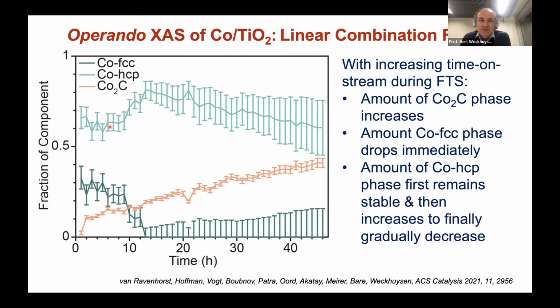And now you have just to believe me that this is then the one which, in our opinion, fitted the best. And what you notice is that cobalt carbide increases as function of time. And then something peculiar happens. Seemingly, the FCC is first consumed at the expense of the carbide. The HCP cobalt is still around, and then drops. So first you consume seemingly the FCC and then the HCP.